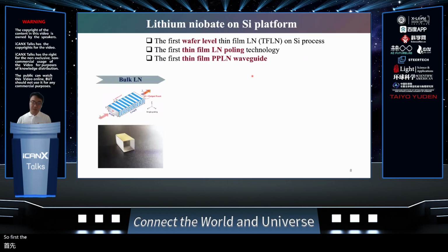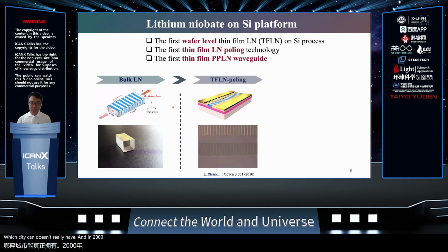The first material I worked with was lithium niobate. This material is desirable because of its large electro-optic and second order nonlinearities, which silicon doesn't really have. In 2016, we demonstrated the wafer-level thin film lithium niobate process. At that time, a really big challenge for this material platform in integrated photonics was how to harness the second order nonlinear effect. Previously in bulk optics, this was done by periodic poling of the bulk crystal. However, this kind of technology could not be directly transferred onto thin film on silicon. So I developed a special technology called surface poling, which can periodically flip the domain within submicron scale for thin lithium niobate.